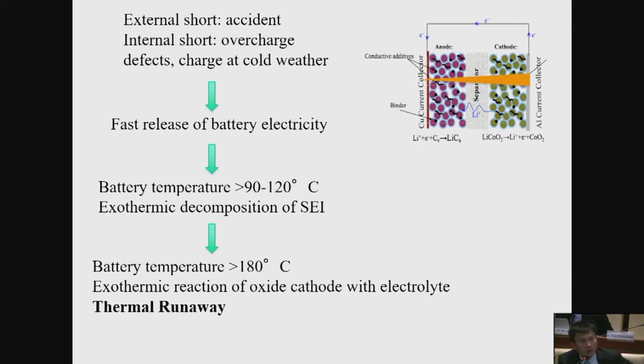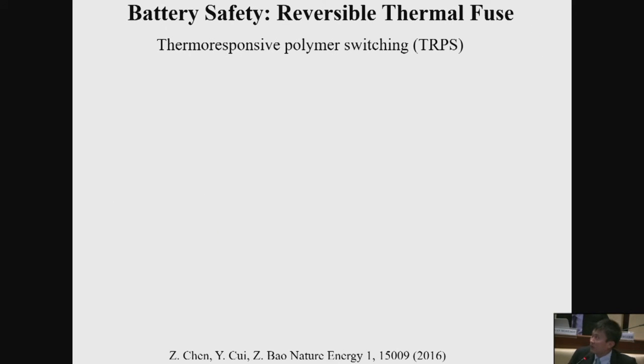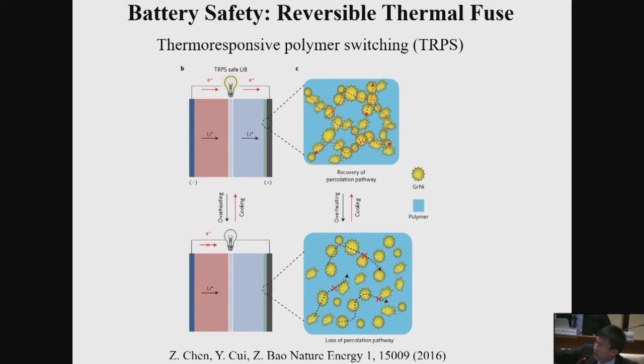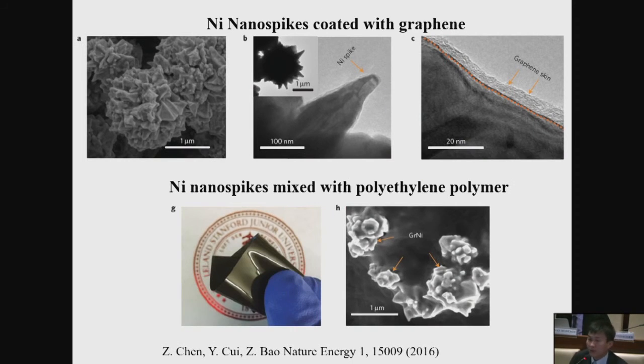So we ask the question: can you make sure the battery does not go over 180 degrees C, ideally not even over 100 degrees C? We came up with an idea, working with my colleague Professor Zhenan Bao in chemical engineering: can you coat your metallic foil or current collector with a layer of insulating polymer, the blue color, with nickel nanospikes inside? If the battery heats up, the volume expansion of this polymer will pull open the nanospikes, and then you cannot pass current through. Even if shorting happens, you prevent direct shorting from current collector to current collector, taking electrons out of the battery materials. So we actually developed such a coating with nanospikes of nickel in this polymer, polyethylene or polypropylene.